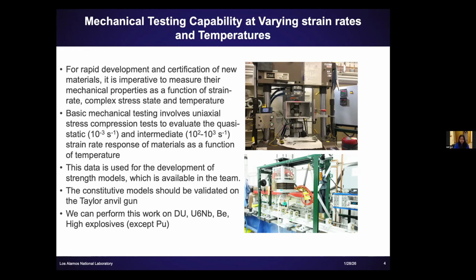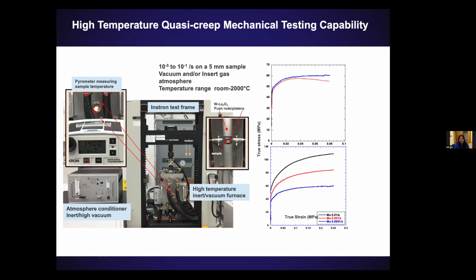strain rate. We can perform work on depleted uranium, U-6 niobium, beryllium, high explosives. We just don't work on plutonium. Thank God for that. We also do a lot of work in the nuclear energy area. We have some unique capabilities where we can do testing on fuel at really high temperatures, up to 2000 degrees C. And we can also go to really low strain rates of 10^-5 to 10^-1 per second. That's important because in NE, when you're looking at fuels, be it for reactors, be it for space reactor applications, these materials are going to be subjected to really high temperatures. So we kind of built that capability.